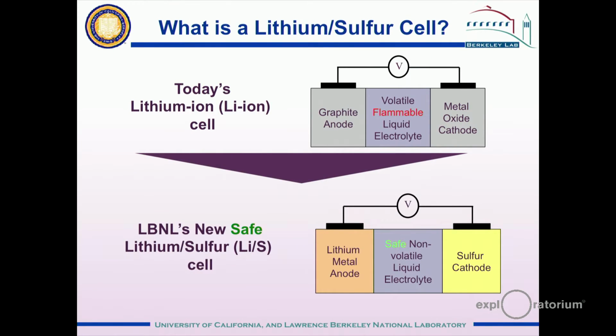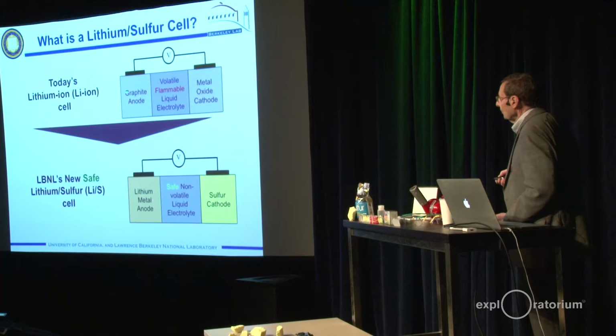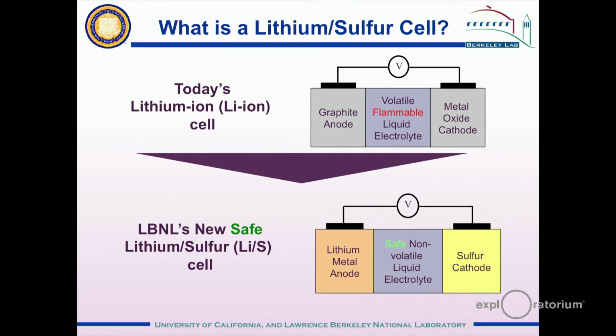So how does a lithium sulfur cell compare to a lithium ion cell? In the upper part of this slide, we see our lithium ion cell. We have graphite, which acts as a host material for the lithium. So the lithium is held between the layers of the graphite. So all of the carbon of the graphite is just dead weight. The reactive material in the negative electrode is actually the lithium. But the graphite anode is only 10% lithium by weight, and it's 90% carbon. So that's a lot of dead weight.